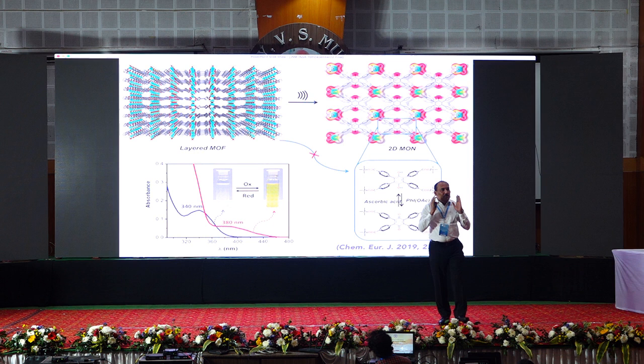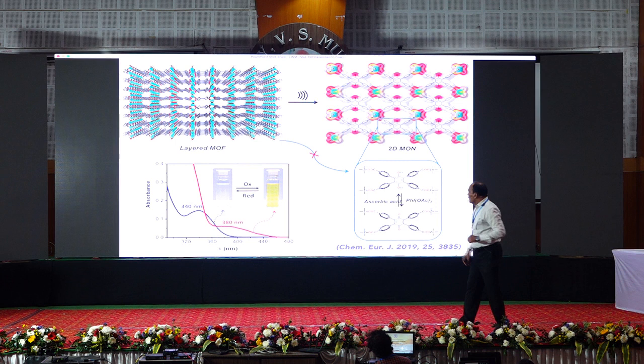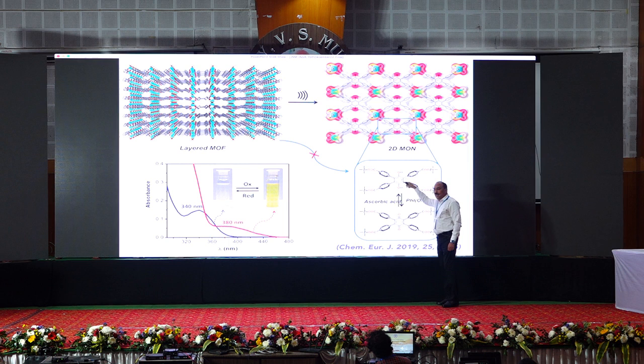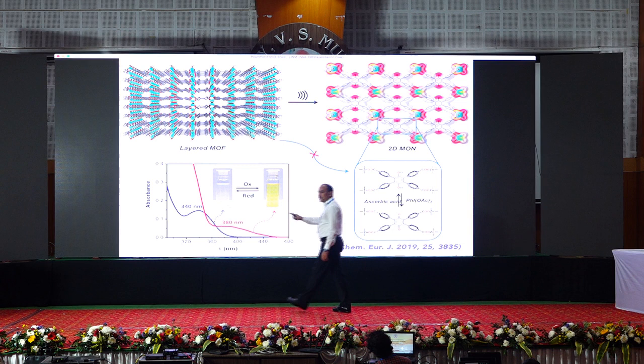Now, I show you the redox chemistry. If you have a hydroquinone, easy it is, you basically oxidize, put an oxidant, and two hydrogens you take away and reorganize the structure, you get a quinone. Quinone is yellow. And of course, reduce it back, you should be able to go back. All that you can do, just the layers extracted into a solution, and this is the 2D material that you have. Basically, put an oxidant, you get to yellow color. Put a reductant and you go back.